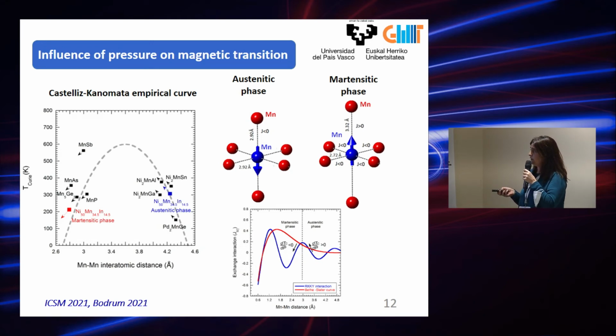So until now, different systems, so different behaviors, but we have in the same material one behavior or the other one depending on the temperature. And this can be explained because of this manganese interaction distance. We can see, for example, that in the austenitic phase and the martensitic phase, there are different distances between the manganese atoms in our structure. So this makes the exchange interaction change, and we can have manganese in one place or in another, with different exchange interactions, and this makes us have these two different behaviors.